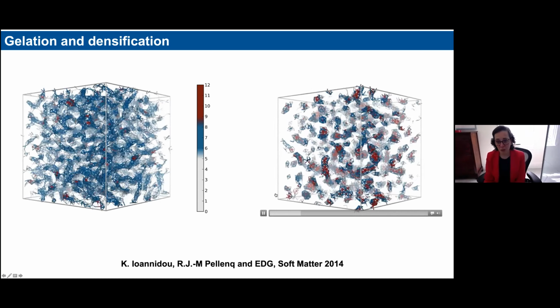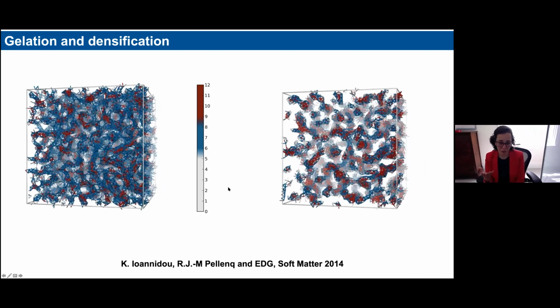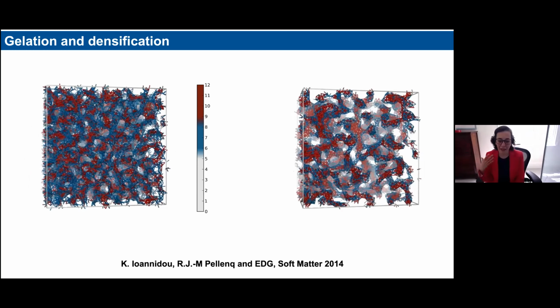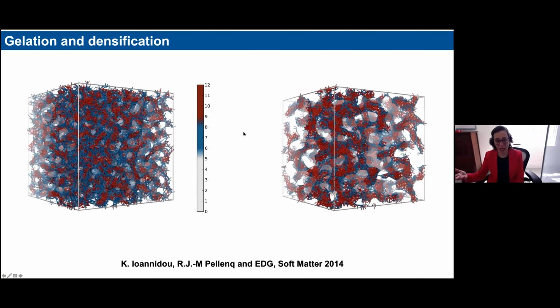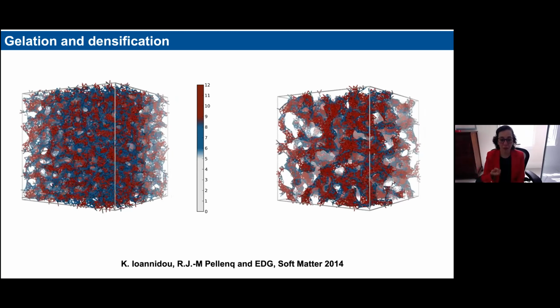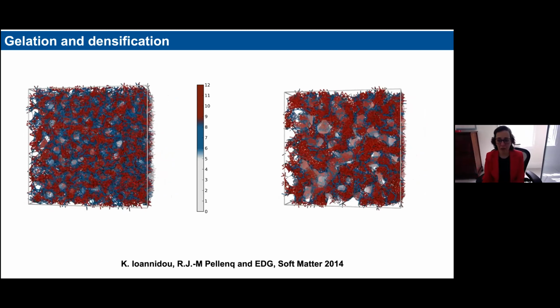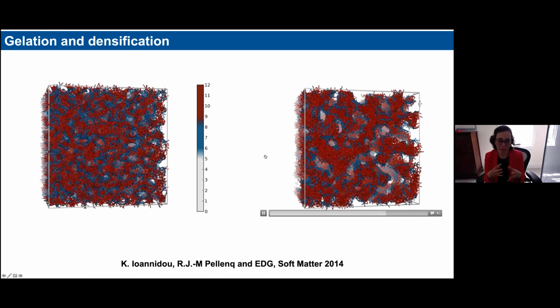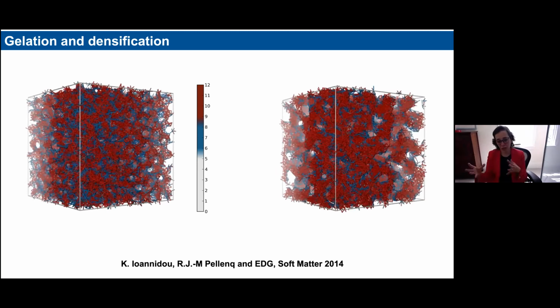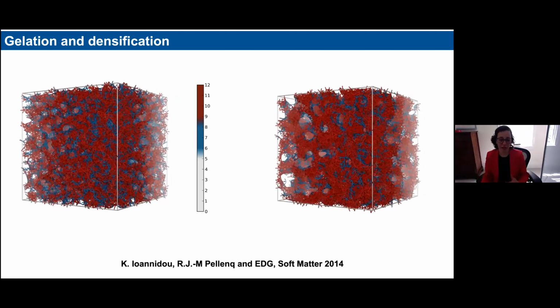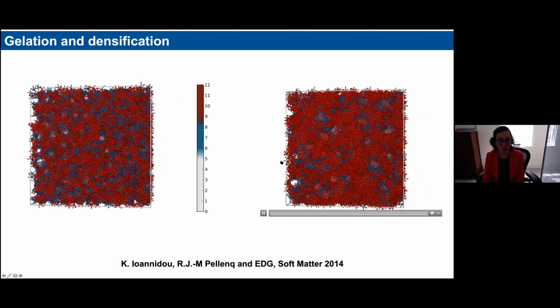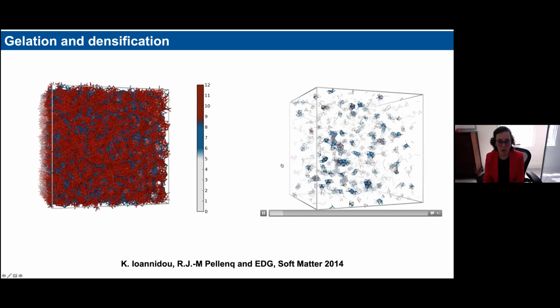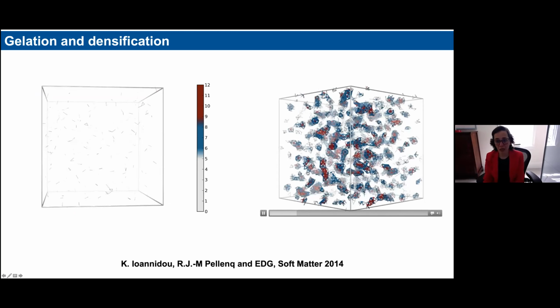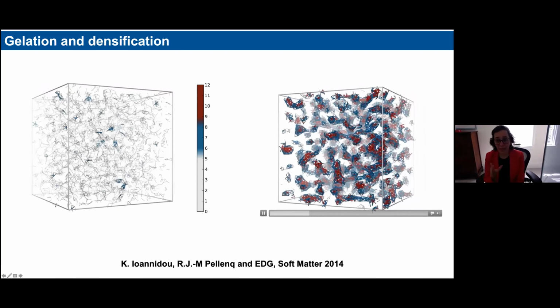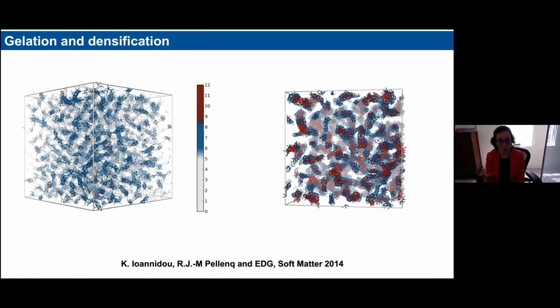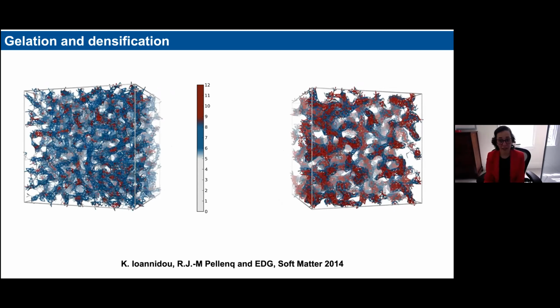On the right, you see the movie of the same thing happening if the forces are instead typical of later stages, when surface charge goes higher and the interactions become a very deep attractive well. Also in this case you start to form aggregates, and then these aggregates branch into a gel, which has some porosity, and then this gel densifies more and more. What we notice is that for the same precipitation rate, the aggregates that you get here on the right are much bulkier and locally denser, and the gel that you form is more heterogeneous and has larger pores.